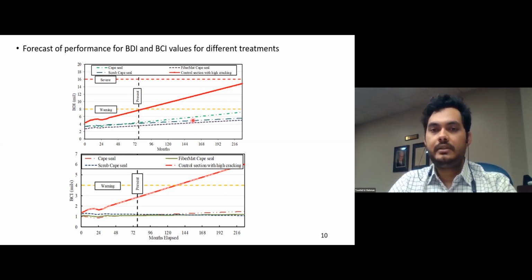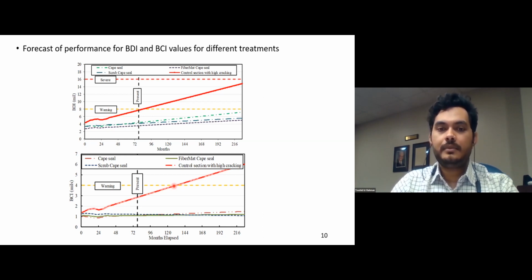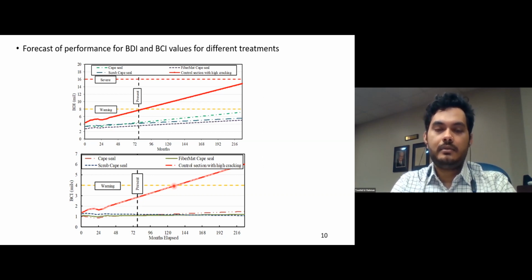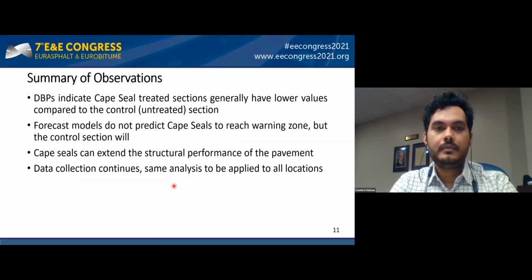Meanwhile, the Cape seal treated sections don't seem to reach the warning zone for the BDI values up to 220 months. The forecast for the BCI values for the Cape seal treated section is quite flat. And yes, the subgrade condition isn't changing a lot, but the untreated or control section is anticipated to reach the threshold of the warning zone in 130 months from the start of operation.